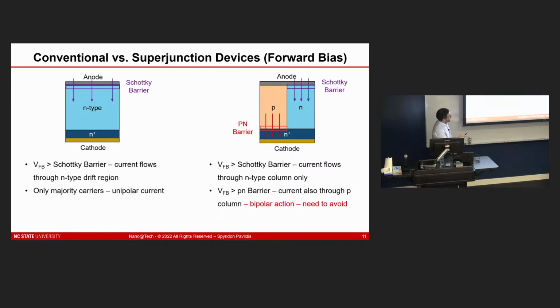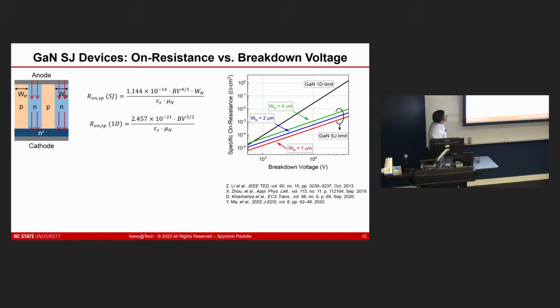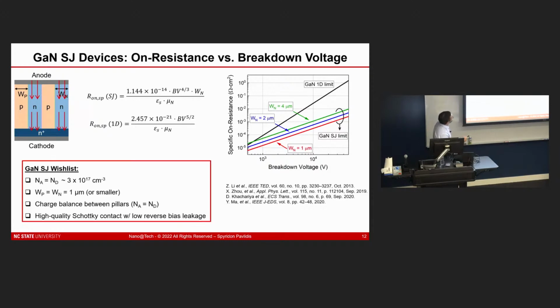The challenge as well, though, is thinking about how to engineer this so that your turn-on voltage is not too low, because if that barrier becomes too low, then your reverse leakage currents also become significant, and you have issues with the efficiency of your device and blocking. So also thinking about Schottky barrier height engineering is important here, and I'll address that later too. So, I'll show a couple of these charts here just to kind of drive this message home.